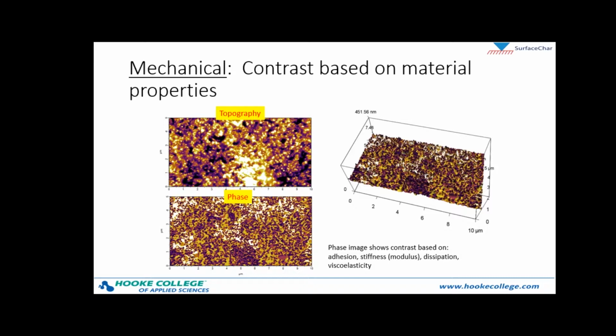And so here I have an image where I've collected the topography and then what's called the phase channel of a tire tread sample. This is a 10 micron by 5 micron image. The phase channel gives you contrast collectively based on a bunch of material properties such as adhesion, stiffness or modulus, dissipation, and viscoelasticity. And so you can see in the topography channel, what we have here are a lot of these little carbon black particles from our tire tread material.